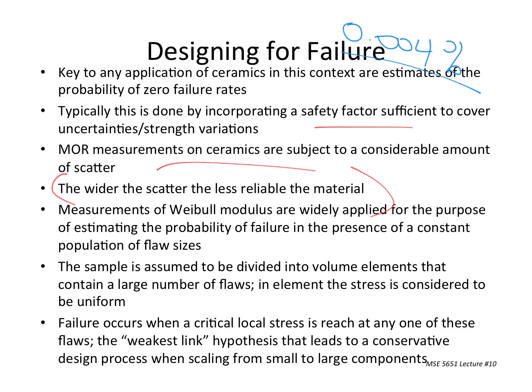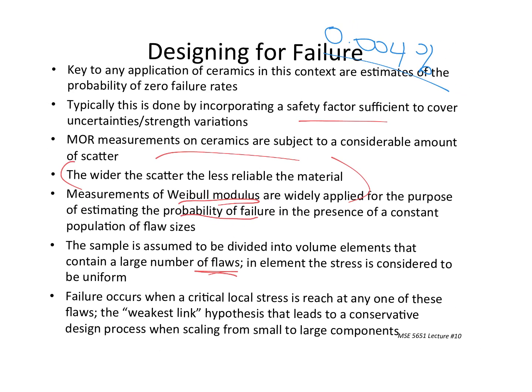So we have 1,000 parts. Assume we break them all. All right. Some will have a high strength, some will have low strength. The majority will fall in the middle of that Gaussian. And what we do is we measure something called Weibull modulus to estimate the probability of failure. And we assume there are always flaws in the system. There are always flaws in these systems. Grain boundary is nothing else. And then what we say is the weakest link is what leads to failure. So the largest flaw is revealed, found out, discovered by that stress, and that's where failure takes place, is that largest flaw, wherever it is in this area that's being stressed.